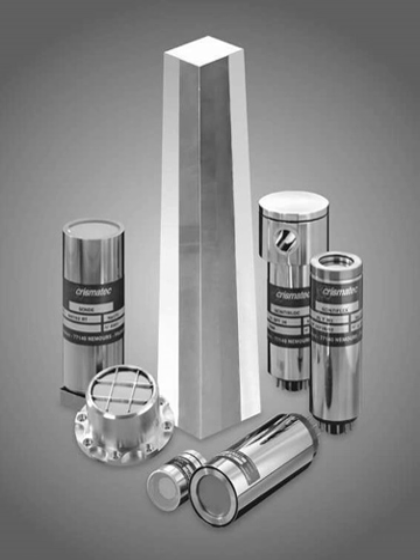Resistance and good behavior under high temperature, high vibration environments is especially important for applications such as oil exploration, wireline logging, measurement while drilling. For most scintillators, light output and scintillation decay time depends on the temperature. This dependence can largely be ignored for room temperature applications since it is usually weak. The dependence on the temperature is also weaker for organic scintillators than it is for inorganic crystals, such as NaI(Tl) or BGO.